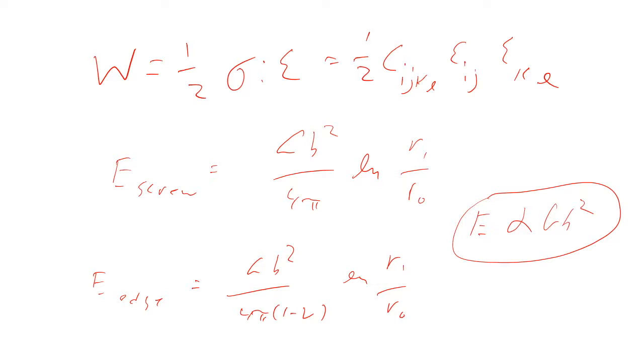Immediately, we see why the dislocations that we see in most systems tend to be on the close packed planes, right? With Burgers vectors along the close packed directions, right? Shortest Burgers vector, right? Why twinning in hexagonal metals in some cases is so much easier than prismatic slip, because the twinning dislocations have a much smaller Burgers vector than c plus a dislocations in these systems, right? So we haven't talked about these things yet, but this is going to keep coming up over and over and over again. Gb squared. Oh, the other important rule of thumb, whenever it's polymers or glasses, free volume, right, is my go-to starting point. Okay.